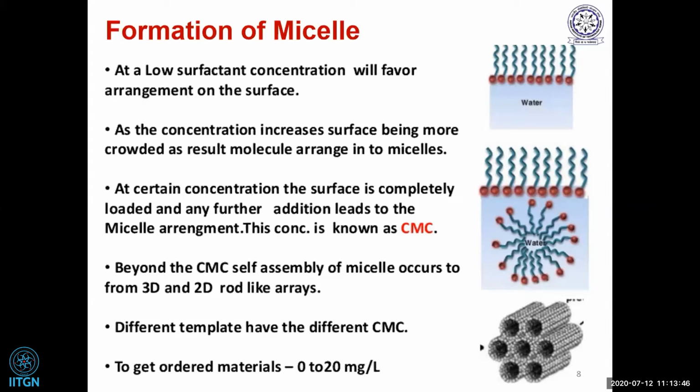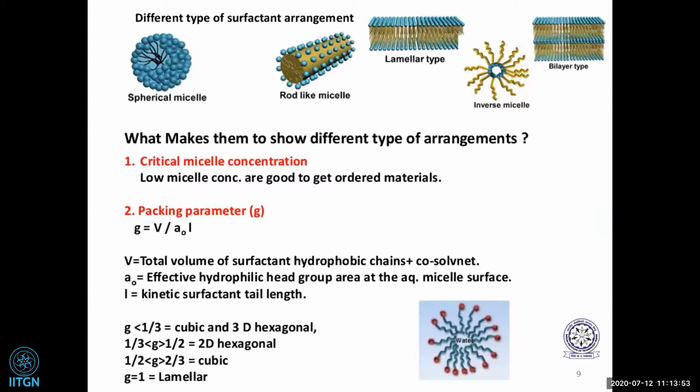Due to their different arrangement in aqueous and non-aqueous media, there are certain parameters which govern their crystallographic arrangement or their mesophase in the medium, for example critical micellar concentration and packing parameter. These are the two governing parameters which decide which form of the phase will exist in the reaction medium. The packing parameter tells about the occurrence of different mesophases, and it can change from one phase to another, as we have observed in certain cases.